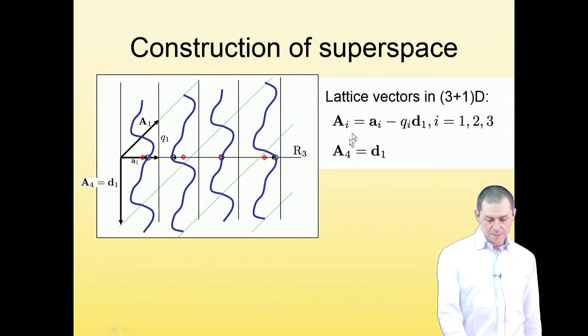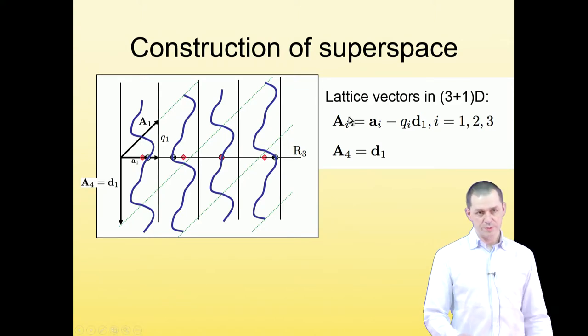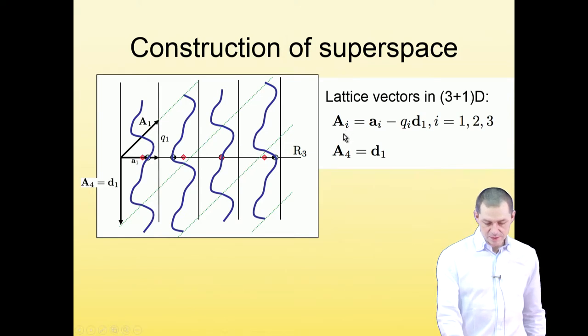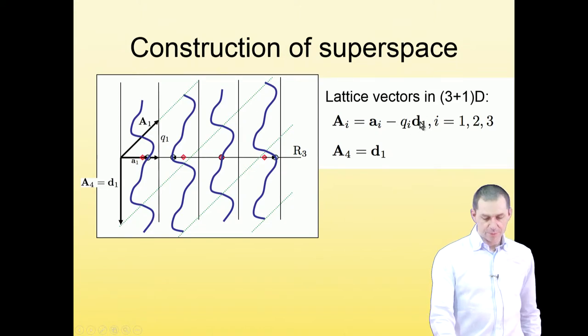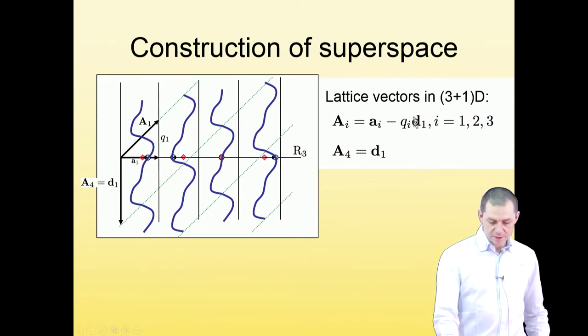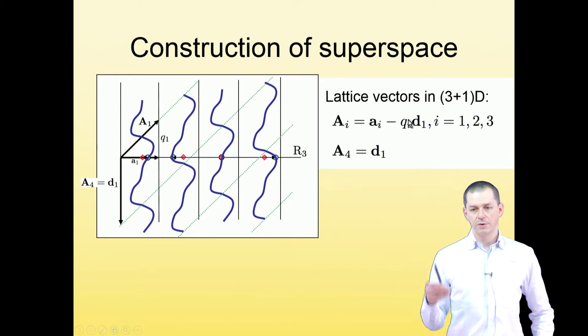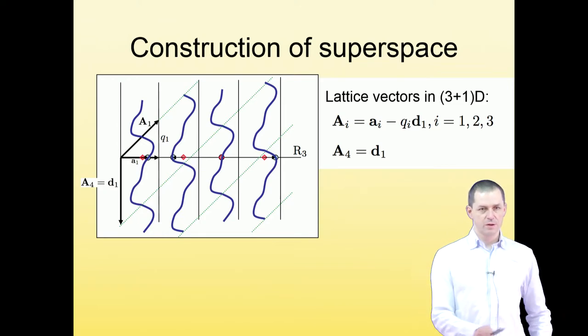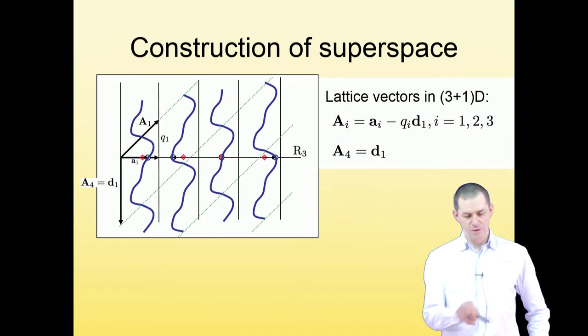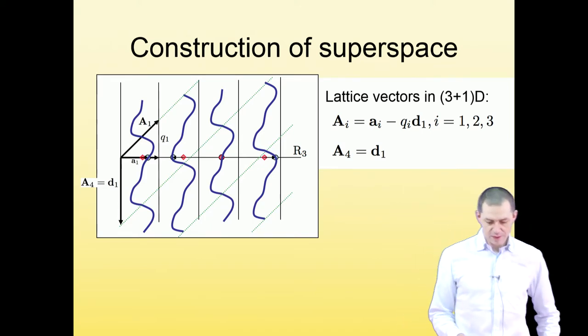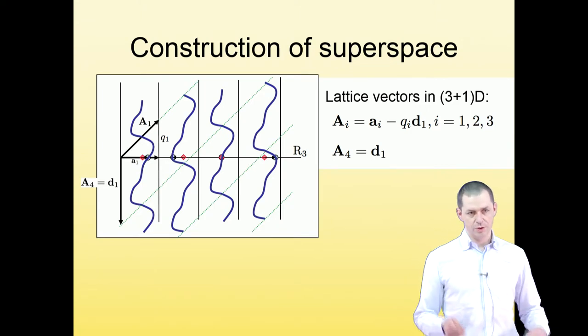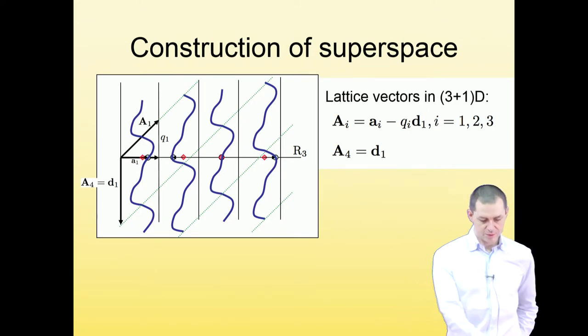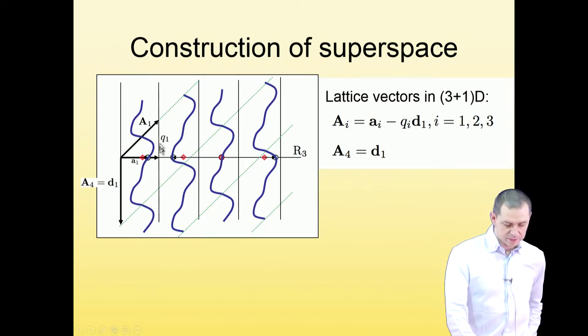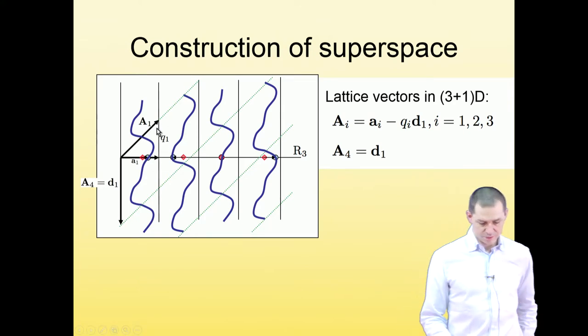So the new basis vectors of the new superspace unit cell are obtained like this. You add a certain additional vector which is perpendicular to the physical space, and how much you add depends on the quantity Q, which are the components of the modulation vector. The little green arrow that you saw in the first images in the description of the diffraction of modulated structure, that little vector had certain components, and it turns out that this height here is defined by the components of the modulation vector.